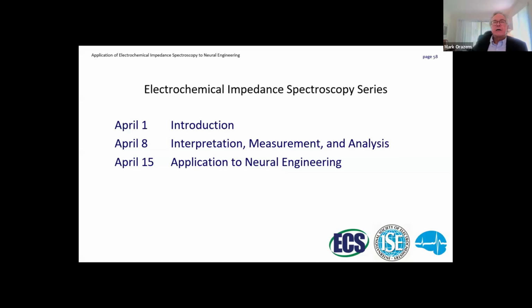I guess what I would say is a couple of things. One is the Kramers-Kronig relations are your friend. I'm a firm believer in using impedance to monitor things that are changing with time. But you have to realize that your impedance data, especially at low frequency, can be influenced by non-stationary behavior. So when you're making the measurements, find out what frequency range is sufficiently consistent with the Kramers-Kronig relations. All the vendors that sell impedance instrumentation, I think all of them now, provide some way of checking for consistency with the Kramers-Kronig relations.